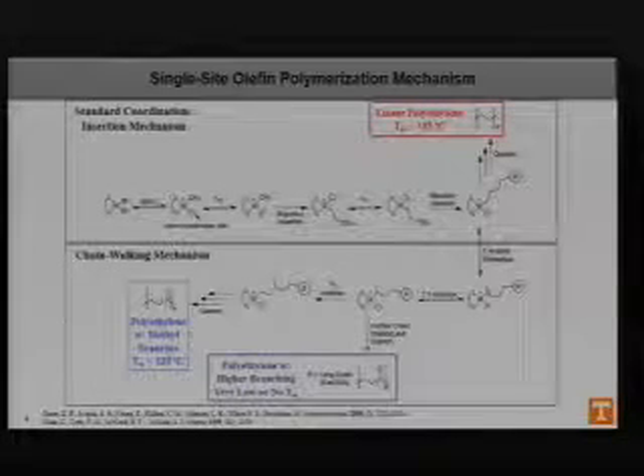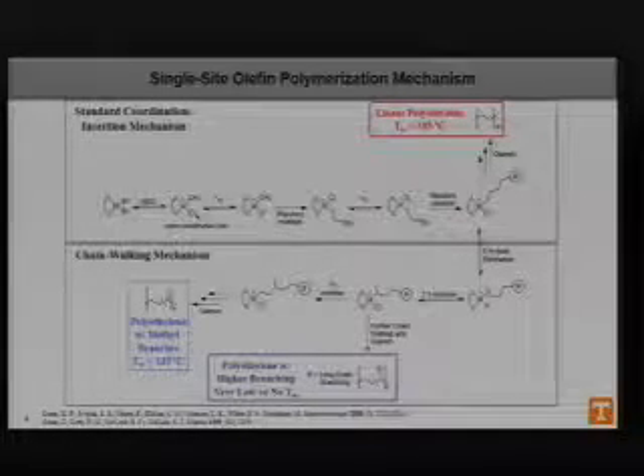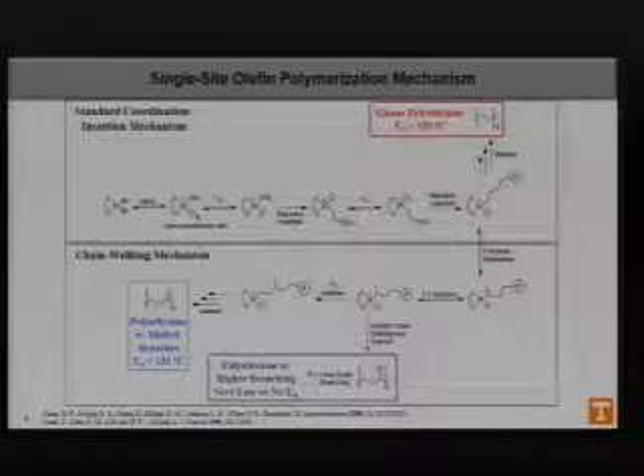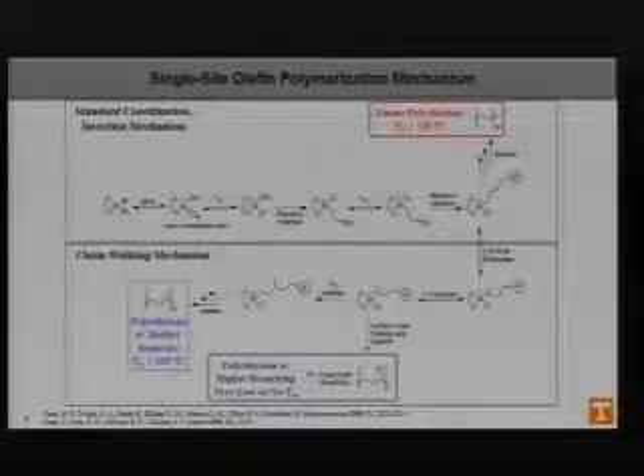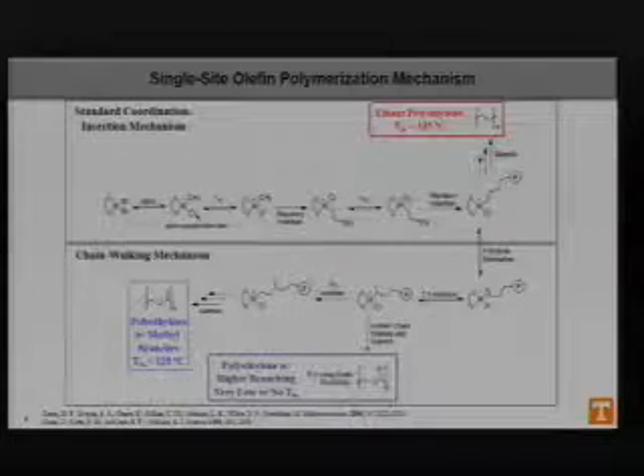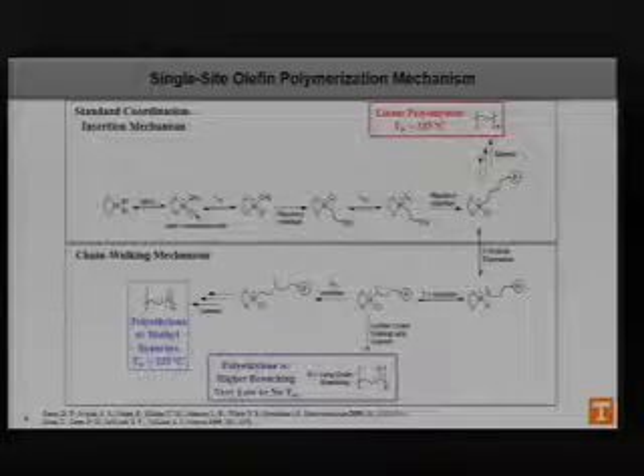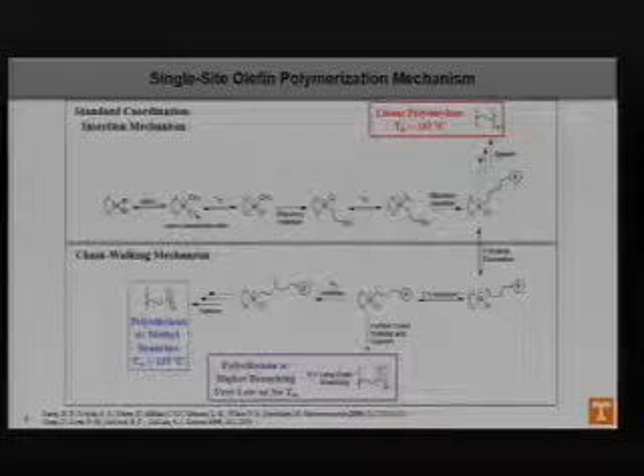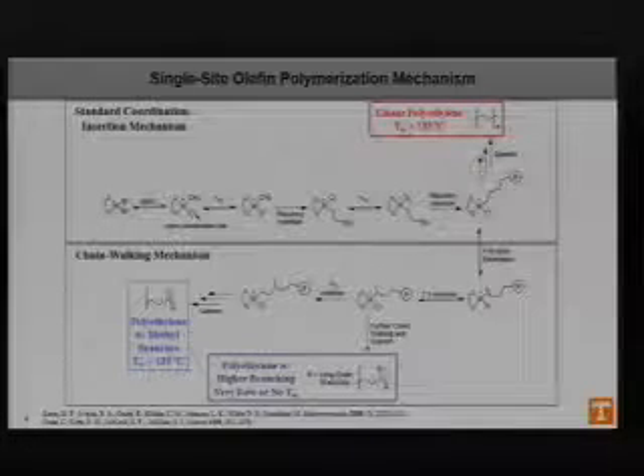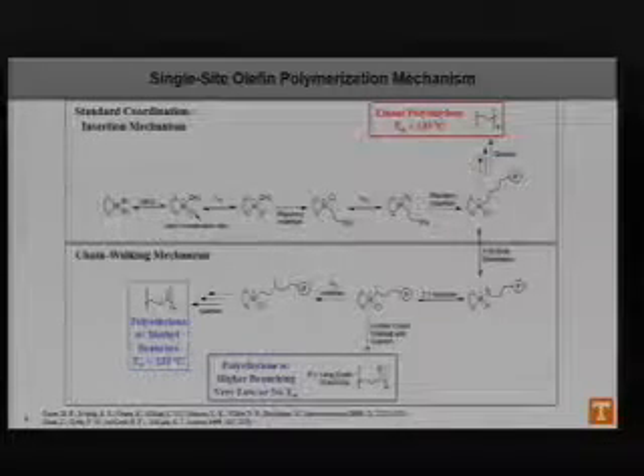Now, group 10 catalysts actually have an alternative pathway available to them, where at any point during this polymerization, they can undergo a beta hydride elimination to create the alkene coordinated species here. And then by doing a 2-1 insertion, create essentially the methyl branch, the first branch of this polymer. And it can continue what's called chain walking down this polymer chain, or it can reinsert ethylene and then leave it as a methyl branch there. And this can happen to any degree, which is where you can get methyl branches or branches that are significantly longer than that. And all of these can drastically affect the polymer characteristics.